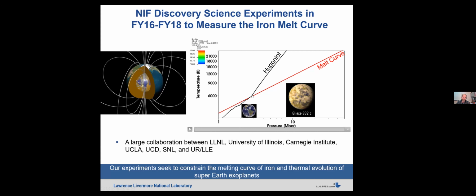In these experiments, we use the lasers to drive a single shock into the sample. So what you're going to see is Lagrangian tracer particles following the path. We drive a single shock, and then we allow that material to decompress. Then we put a ramp compression, or a shockless compression wave, back into the material, compressing it to high pressures and temperatures. And at the peak stress, we probe it with our X-ray source to test whether it has solidified.